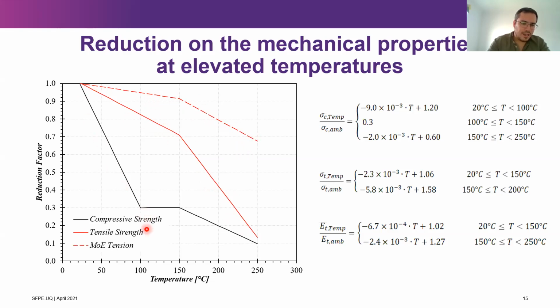So what you can see here is that, for example, at 100 degrees, bamboo loses almost 70% of the compressive strength. And that's a significant reduction. Like if we think that the temperature during a fire is, you know, at 1200 degrees Celsius, this is telling us that we very quickly start losing the capacity of load-bearing bamboo members.